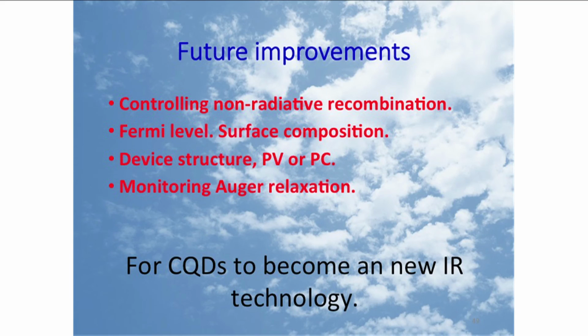So, future improvements in this topic. We need to control the non-radiative relaxation. This is very important. This is this issue of the quantum yield dropping dramatically. We will need to learn better how to use the surface to modulate the Fermi level. We need to improve the device structures. And we need to monitor the Auger relaxation, which is why, a priori, these materials are much better than bulk. And I think we will have a technology for infrared.